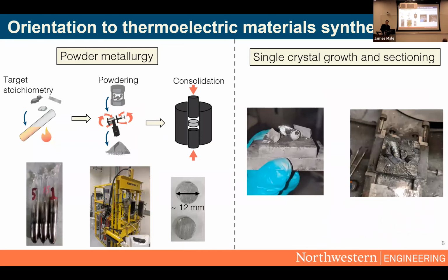I also think it's a little useful to orient people to the appearance of these materials as I talk about measuring them. So generally the thermoelectric materials I made for this thesis were through two methods, either a powder metallurgy type method where I melt together materials in a certain composition, powder them up by ball milling or hand grinding, and press them in a hot press to get these nice dense cylindrical pellets. I also have a couple instances where I grew single crystals of my material or very large grain ingots of my material, in which I was able to align them and cut them up with a wire saw.